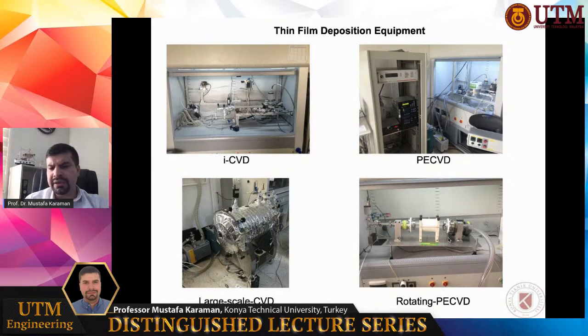In the bottom right, you can see a rotating PECVD system. This CVD system is very similar to a classical CVD system with a basic difference. Here, a glass vacuum chamber is rotated back and forth during the deposition under vacuum. We usually place a powder substrate here, particulate solids, in order to make some functional coatings on them. But to obtain highly uniform coatings, the whole system should be rotated. So it's like a washing machine, but working under vacuum and in the presence of a plasma. So in this system, we obtain highly uniform coatings around very geometrically complex particulate solids.